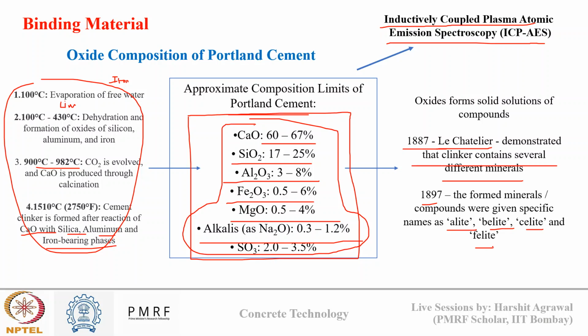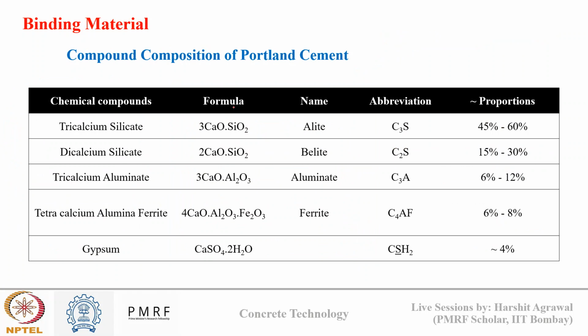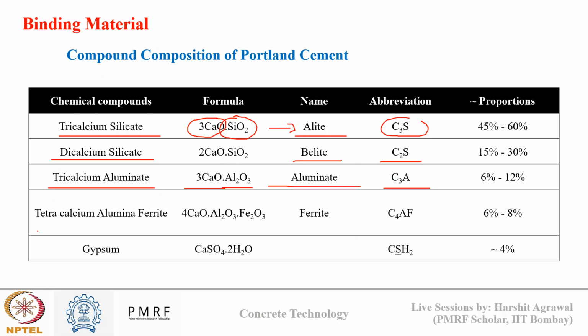The proportion of these formed solid solutions of different compounds is shown in this table. We have tricalcium silicate, where 3 moles of calcium oxide combine with 1 mole of silica. This is abbreviated as C3S, and it is known as alite. Then dicalcium silicate, represented as C2S, is known as belite. Tricalcium aluminate, where 3 moles of CaO and 1 mole of Al2O3 are present, is abbreviated as C3A. Then tetracalcium alumino ferrite is represented as C4AF, and there is gypsum, whose chemical formula is CaSO4.2H2O, represented as CSH2 with a bar over the S.